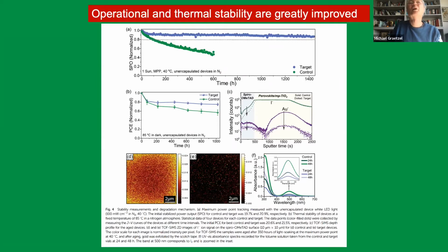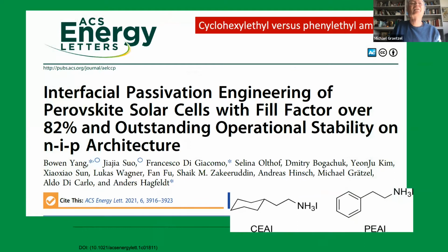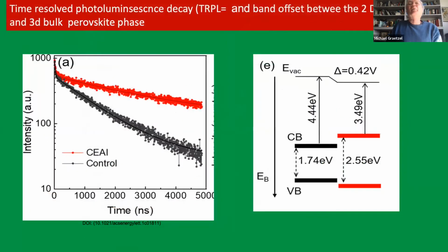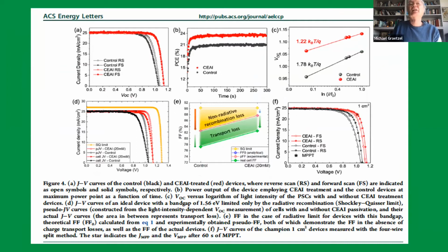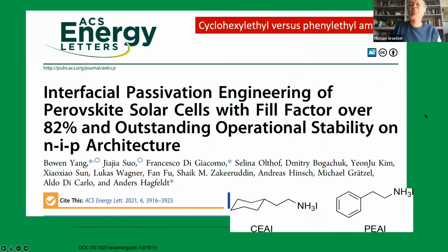And so a simple molecular modulator like this can buy you this big stability increase. And yeah, the other molecules, I won't insist on, they're all similar. Here's a different one; this was a paper where we used cyclohexyl ethyl ammonium iodide. And so you can imagine that the ammonium group inserts into the surface of the perovskite by replacing the A cation. And so it makes some kind of a self-assembled monolayer.